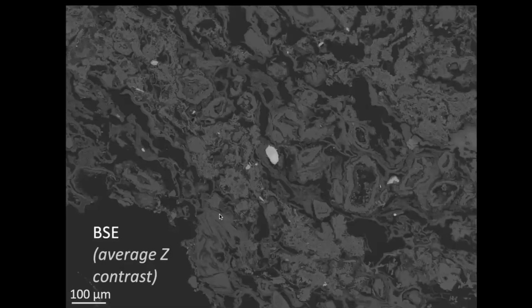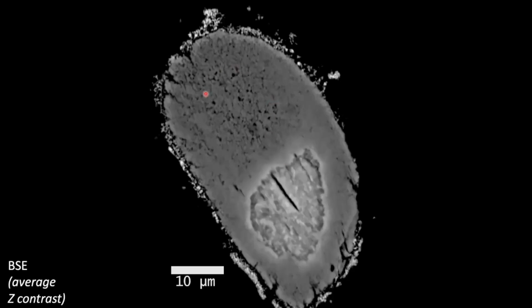I found another grain that was also surrounded by a lot of impact melt, and I went, that's probably granular. This one's interesting because it's a lot more porous on the inside. It clearly had some kind of inclusion. And then it's also got this brighter contrast stuff on the outside. This is pretty normal to have a decomposed rim of zirconia and silica. This is most likely what this is.